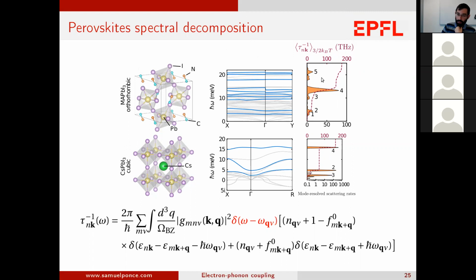And the number that you see, 1, 2, 3, 4, 5, corresponds to different vibrational modes. And what is interesting is to compare the MAPI one with the cesium lead iodide one, and you can see that some of them are the same. So the main peak here is the same as this main peak from the cesium lead iodide. It's the same kind of vibration.